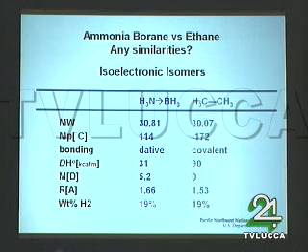And from a chemistry point of view, the bonding is quite interesting in the ammonia borane, in that the non-bonding electron pair donates into the empty p orbital of the boron to make this dative bond, which is weaker than a covalent bond, but it's greater than conventional electrostatic hydrogen bonds and such. It has quite a substantial dipole moment, and the bond length's about 10% longer for that BN bond. And so that's sort of interesting in the starting material.